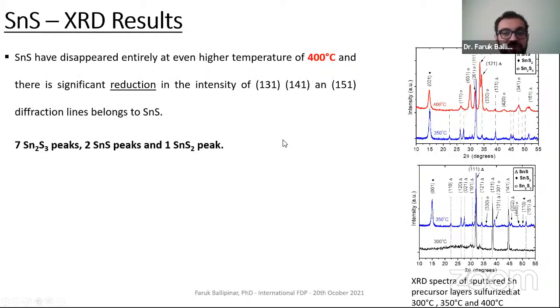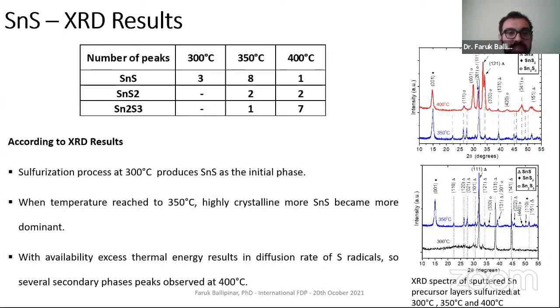At 400 degree, we can definitely see a significant reduction in the intensity of these diffraction lines, and they mainly belong to other phases, called secondary phases, SnS2, Sn2S3. So in terms of the number of peaks, 350 degree shows a higher number of peaks belonging to tin sulfide. According to XRD results, tin sulfide already starts to form as an initial phase at 300 degree, but highly crystalline, more dominant tin sulfide became at 350 degree.